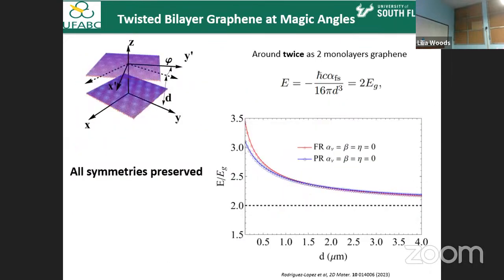So again, I don't want to show you details. And this is my system again. I'm taking the simplest case when none of the symmetries are broken at that magic angle. And what I see is the asymptotic behavior, in other words, all my parameters are zero. I have these 10 bands, tight-binding functions, but all of these parameters are zero, none of the symmetries are broken. So asymptotically, what we get is that the interaction is twice the interaction of a single layer.